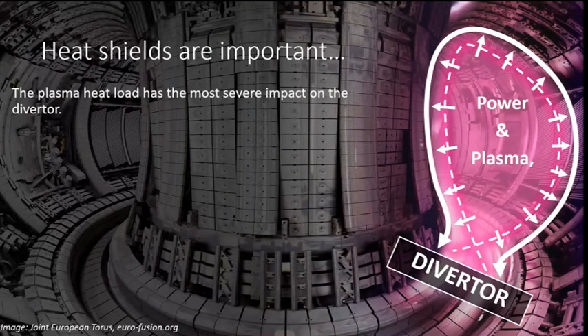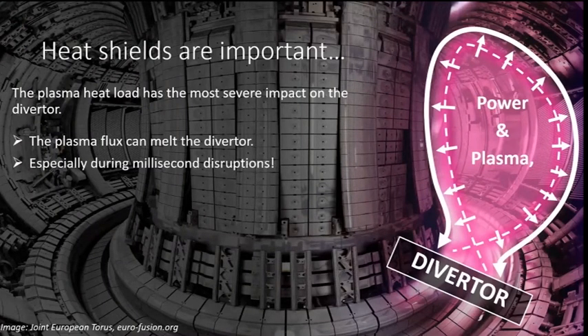And in the diverter, the impact of this plasma and this power is the biggest. So easily the diverter can melt. And moreover, if you lose control of the plasma and it becomes destabilized, in about a millisecond or so, you can destroy your entire diverter, which means there is a $1 billion investment down the drain.